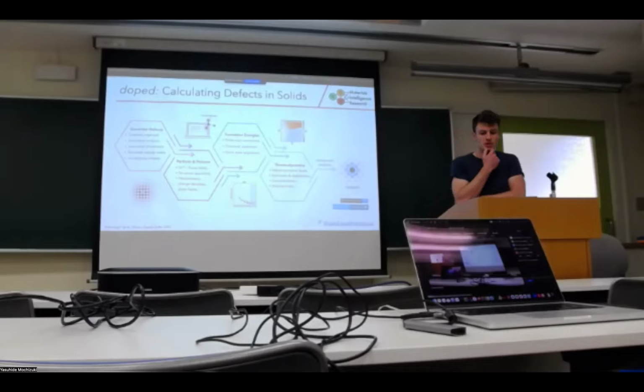That's a good question. I would say that one of the difficult things with defects in general is that often it's very tough to get clear experimental measurements or confirmation of defect behavior. And so often we more predict downstream properties, like, maybe when we find one of these metastable states and then find the ground state, that it changes the dopability of our material, and that matches experiment better.